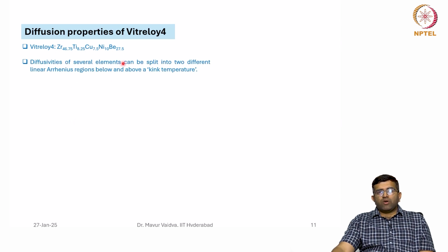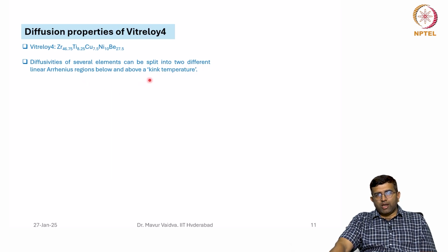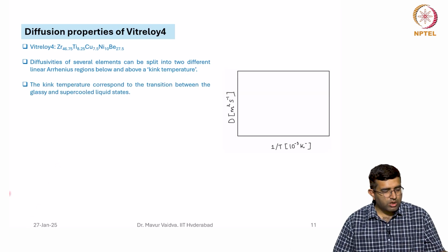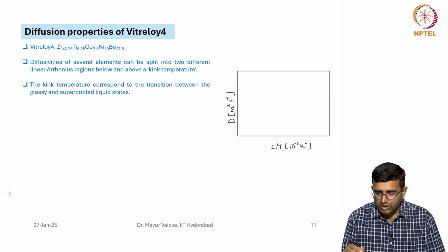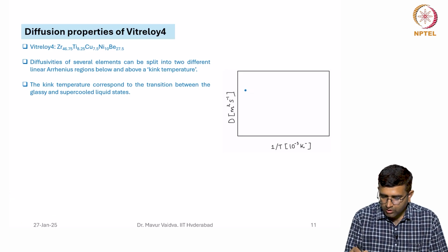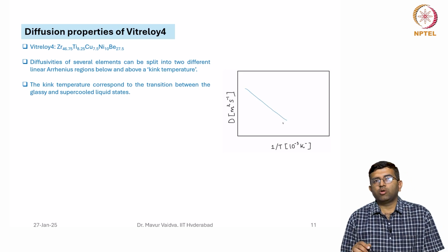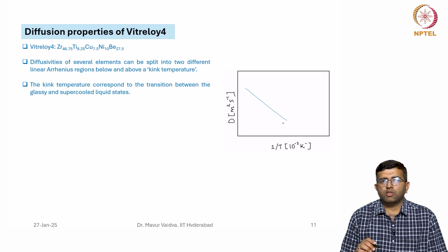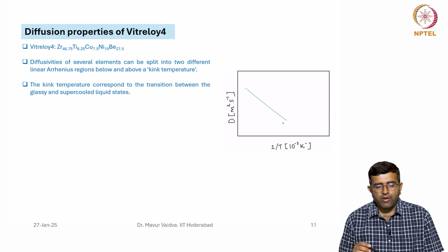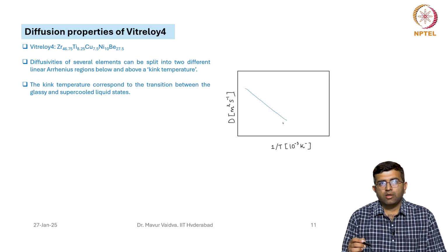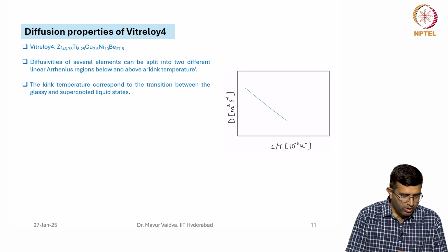So these diffusivities of several elements, which are studied in this Vitreloy 4, exhibit an interesting feature: they can be split into two different linear Arrhenius regions below and above a kink temperature. Just schematically, I can show that normally, if there are no phase transitions and so on, we expect a linear line like this. But in the case of this particular alloy, what has been seen is that there is a small kink that is observed.